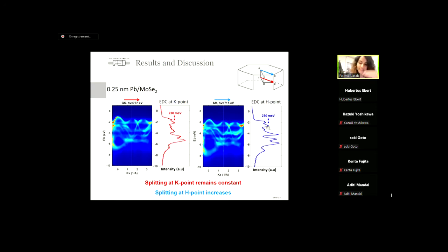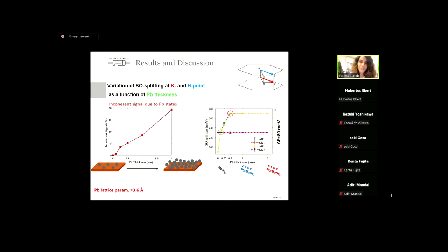We repeated the same thing for different thicknesses of lead overlayers. And this is the summary that I got. So we could increase it from 190 meV at the H point to 270 meV. So we could increase it by 80 meV only by adding 0.5 nanometer of lead on the top.